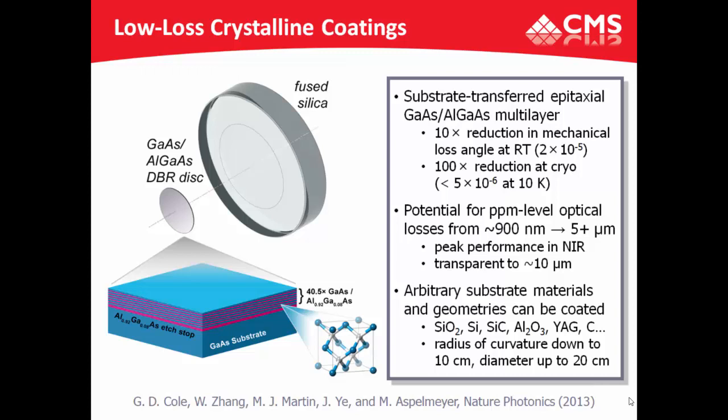I'll show in the course of the presentation we can achieve fairly nice optical quality with these coatings. But the big selling point here is we're looking at a 10x reduction in the mechanical loss angle. So going from something like 4 times 10 to the minus 4 down to 4 times 10 to the minus 5 or below at room temperature. One disadvantage of the dielectric coatings is if you cool these things, their mechanical quality factor